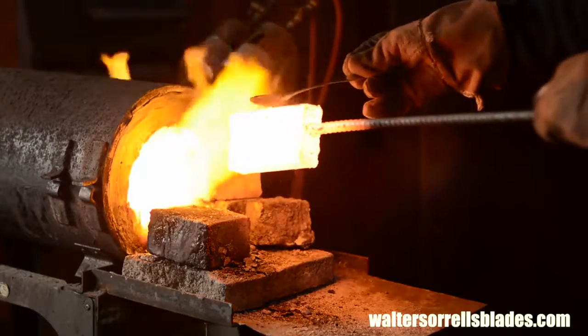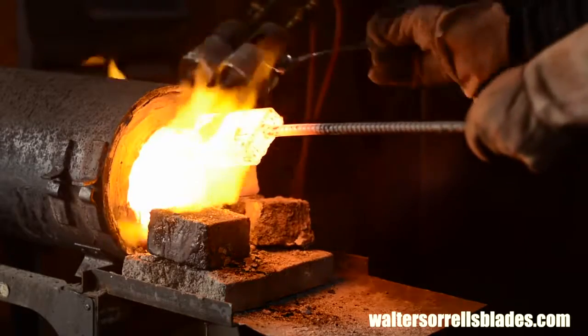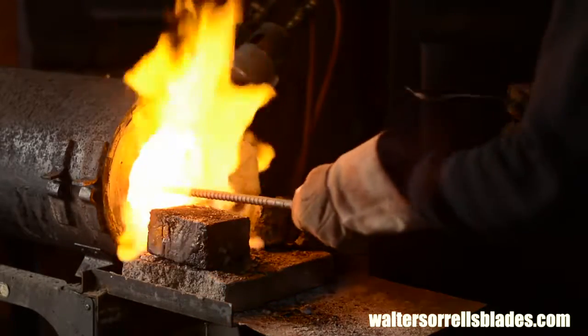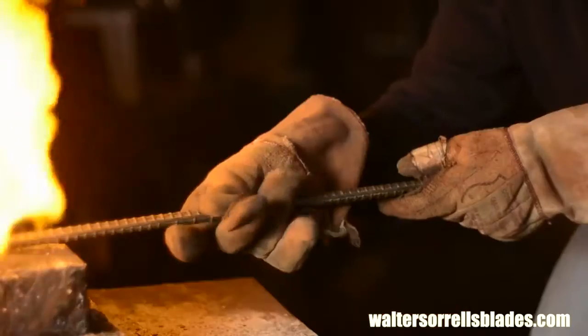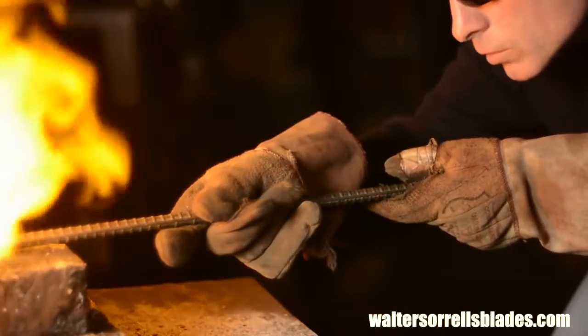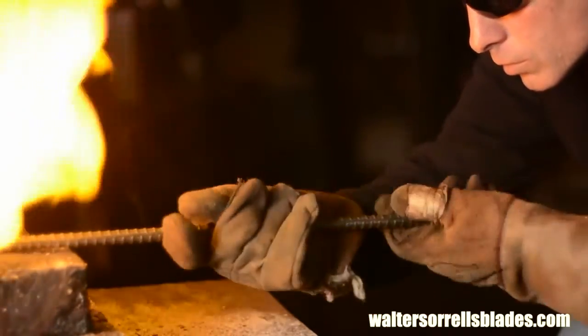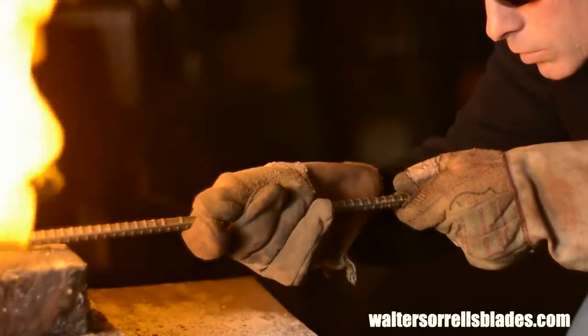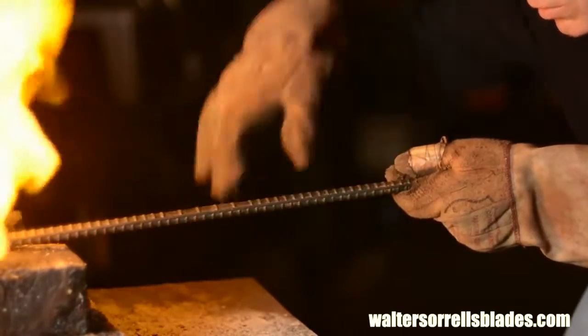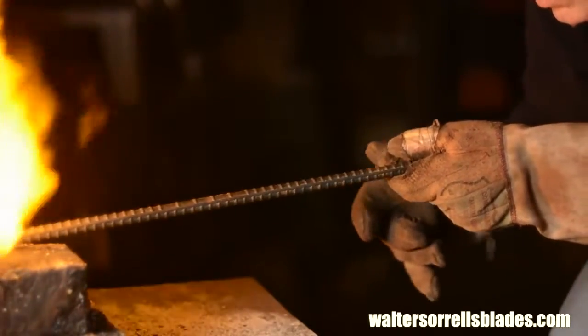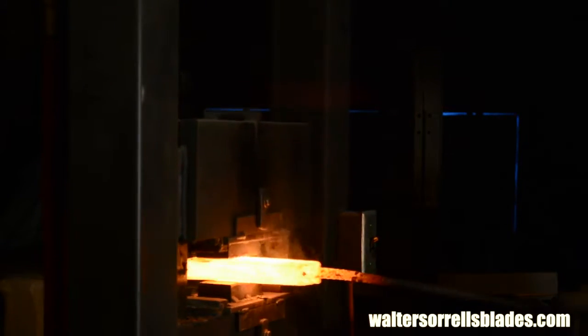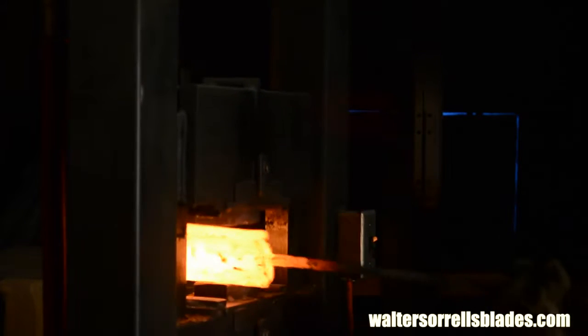Once I've set the welds, I immediately flux the billet and jam it back into the forge as fast as possible. Now you'll see people that just blast away and start drawing out the billet immediately, but I feel like giving it one more heat at welding temperature will make the welds less likely to shear and give you a better product in the end. If you've done it right, it'll come back to a welding heat pretty quickly.